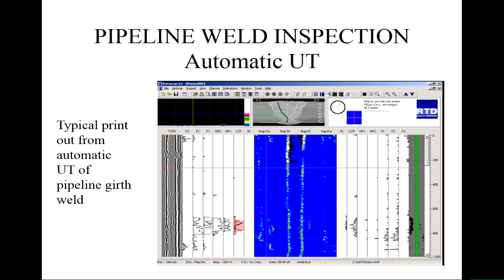There's quite a lot of stuff being printed out. Time of flight will tell you about laminations and things like that as well. That's there. This then has a red bar which tells you when it thinks something needs repairing. So you've even programmed in the failure criteria in this case.